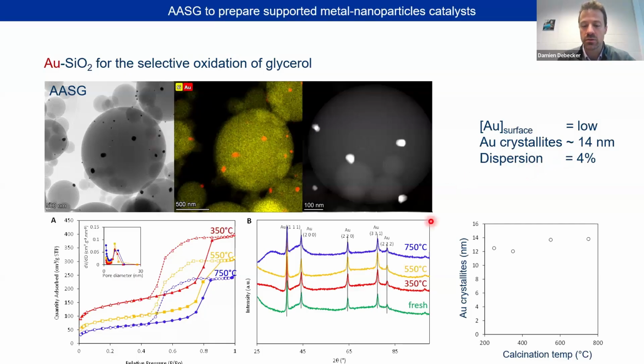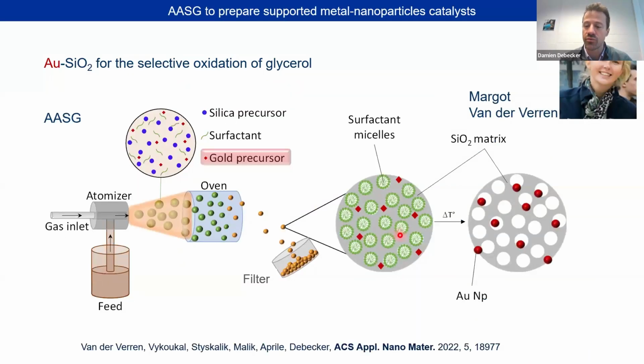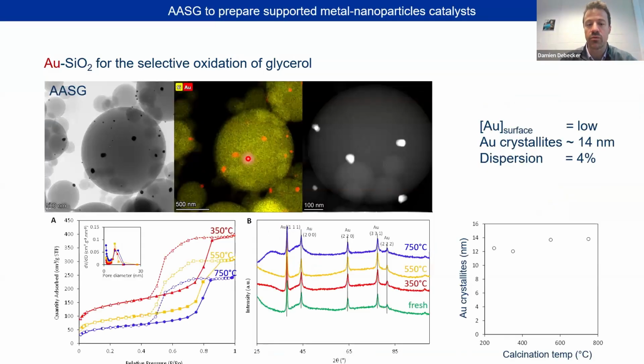I would like to point out that here in XRD, we see the signal of gold, and we see it whatever the calcination temperature, but we also see it even in the fresh catalyst, so before calcination. So we'll go back to the previous slide and show you the fresh catalyst is this one, the one before calcination. So in essence, what is happening is that the gold precursor is decomposed during the treatment in high temperature here. It's not very high temperature, it's 350 degrees C and for a short time, but it's sufficient to trigger the decomposition of the gold precursor and the formation of those big particles because we already see them here. So that's the problem, and we have too big particles.